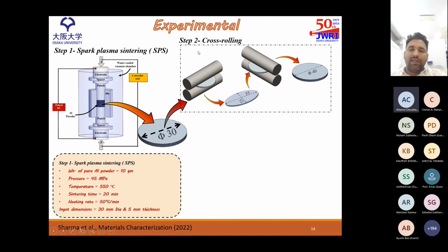In the second step, we have done the cross rolling. What is cross rolling? Cross rolling means the specimen is rotated by 90 degrees after each pass. In the first pass, we obtained a billet with dimensions of around 32 millimeter width on the minor axis, and the major axis has around 55 millimeter. In the second pass, it is rotated and again passed through the rolls, and then we obtained around 40 millimeter diameter and 2.5 millimeter thickness. So it is a 25% reduction in each pass.